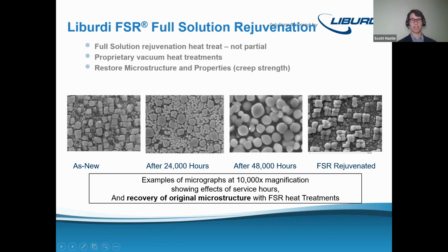And as we maybe can remember from our metallurgy course, any dislocation moving through this material, it would take more energy to go up and around a blocky gamma prime particle than it would to go around a sphere. It just takes less energy, and therefore you'll see that mechanically, which we'll see on the next slide. And then the key part of the full solution rejuvenation is our goal is to take this microstructure, take it above the solution temperature, and then reprecipitate out the gamma prime structure. So we get this blocky gamma prime structure and this secondary gamma prime structure to make sure we're not only returning the creep strength, but also the tensile and fatigue properties of the material.